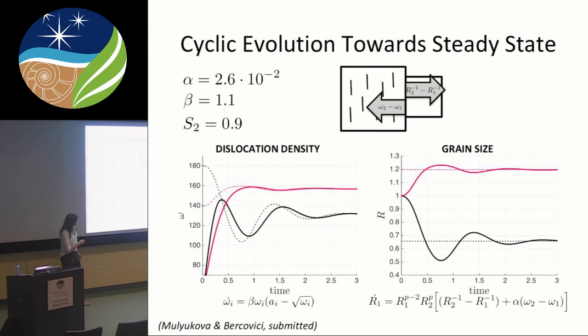So the slightly larger grain starts to grow, but the dislocation density doesn't really have time to adjust to this changing grain size. And so the grain size just overshoots its steady state because the dislocation density is still a little low. By the time dislocation density has time to catch up, you now have a higher dislocation density than what the grain is happy with, and so it starts to shrink again because now the grain has too many dislocations. Okay, so it does this kind of overshooting, undershooting as it evolves towards the same steady state as I showed you in previous pictures.